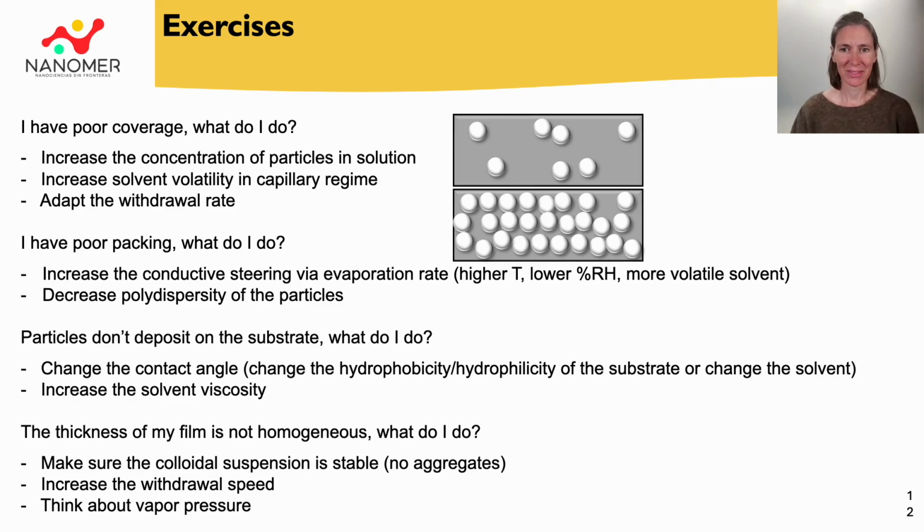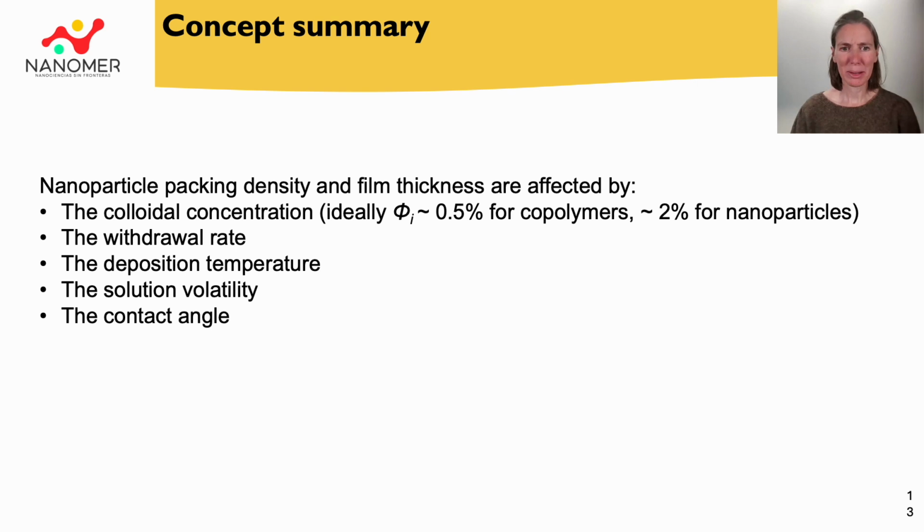deposition. To conclude, nanoparticle density and film thickness are affected by many parameters. These include the concentration of our solution. Ideally, if we're depositing copolymers, we're going to want a concentration of around 0.5 weight%, and for nanoparticles, we'll want to be around 2 weight%.